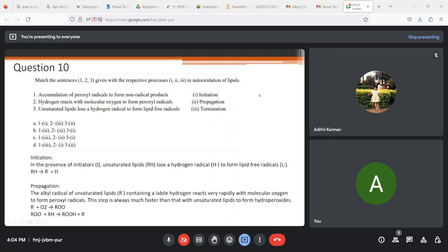So that corresponds to accumulation of peroxyl radicals to form non-radical products. If you can see here, the first step is your unsaturated lipids losing a hydrogen radical to form lipid free radicals. These lipid free radicals have a labile hydrogen that reacts with molecular oxygen to form peroxyl radicals, which corresponds to propagation. And then when you have too many peroxyl radicals present in your food compound, these radicals will start interacting with each other to form non-radical products. So that comes under termination.